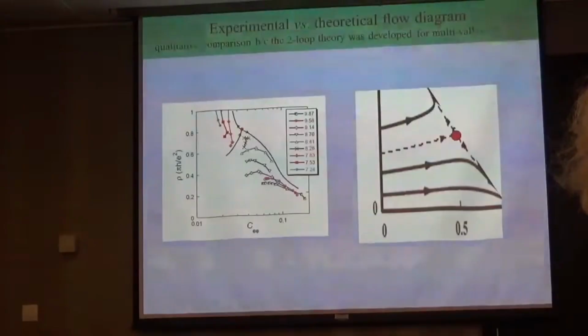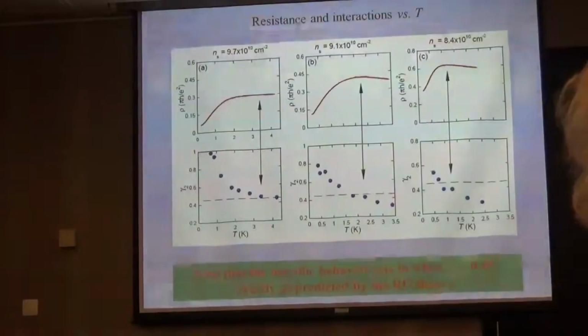But you can see that basically we have the same behavior as on the theoretical phase diagram. At first, resistance grows when temperature goes down, and then it decreases. We don't see a decrease to zero, of course, because our temperatures are finite. But you can also see that they form the same line, more or less, as on this phase diagram. But if disorder is too strong, instead, it continues to grow when temperature goes down, so we follow this line. That's the qualitative phase diagram, but they also made quantitative predictions.